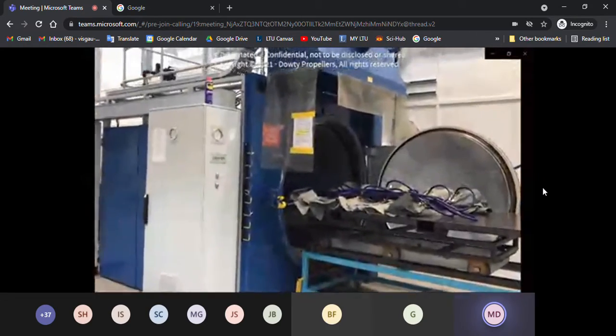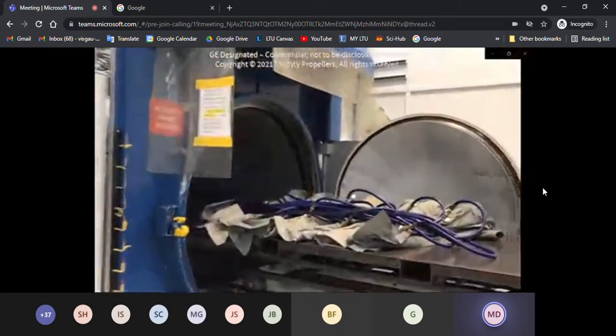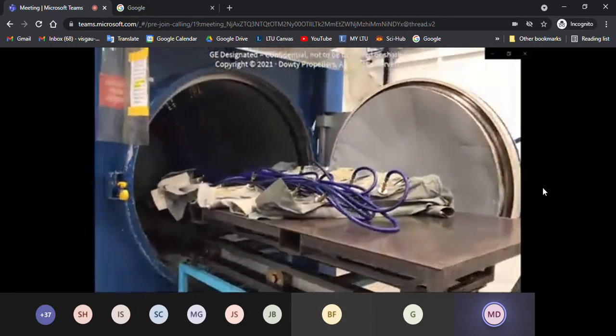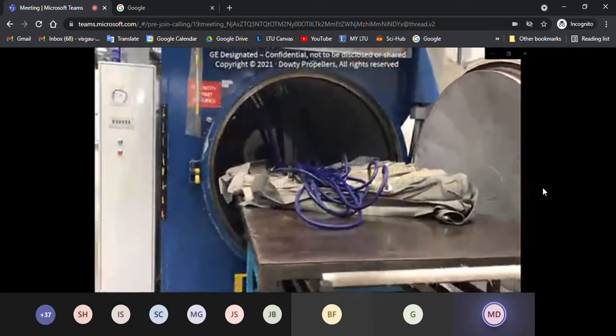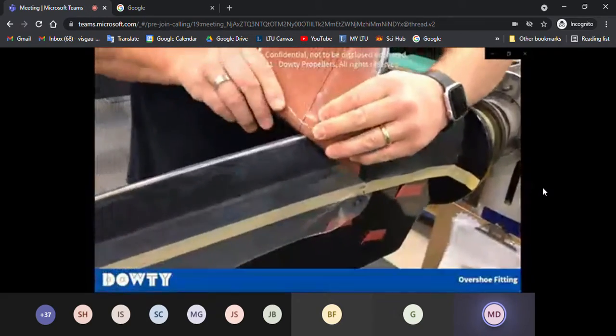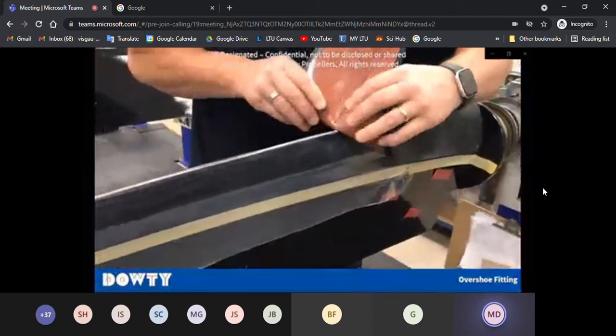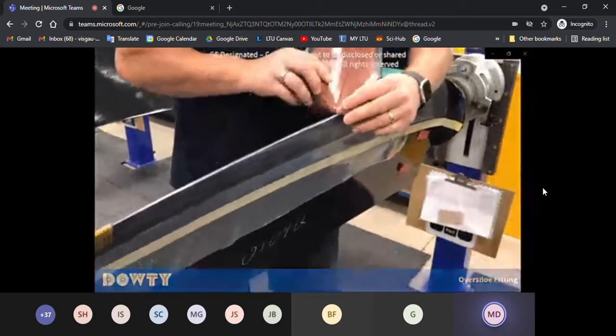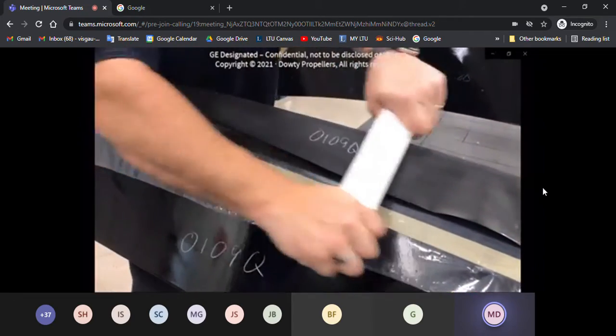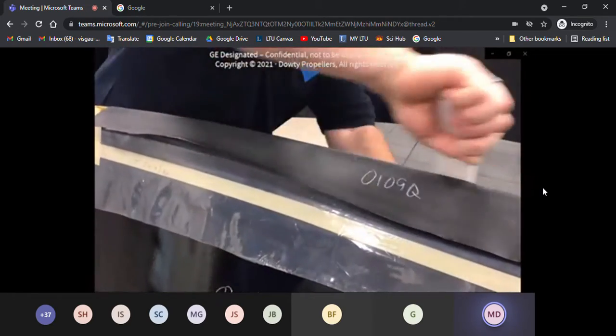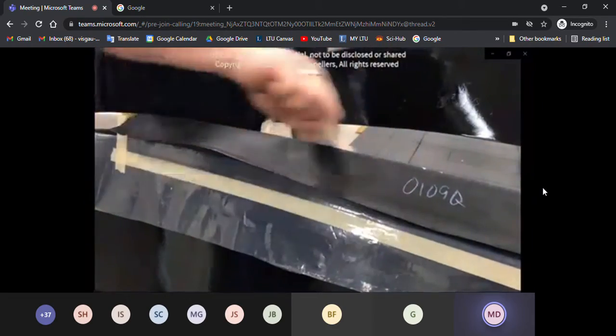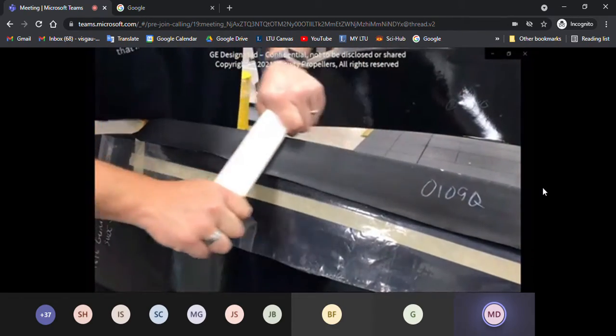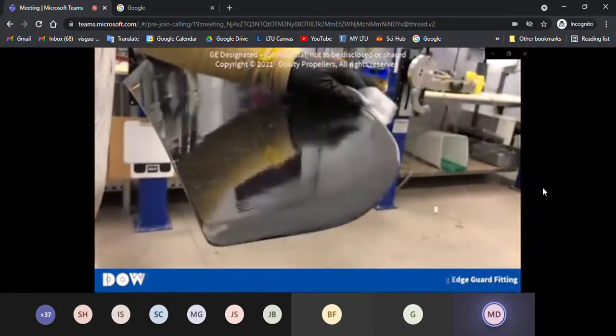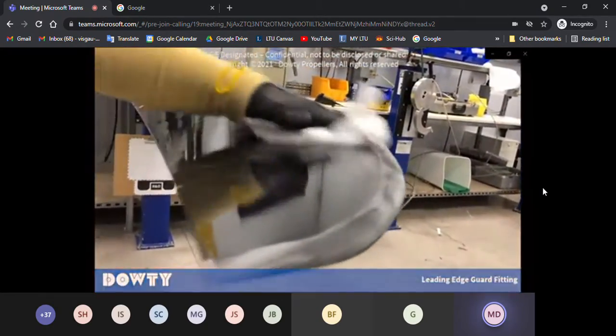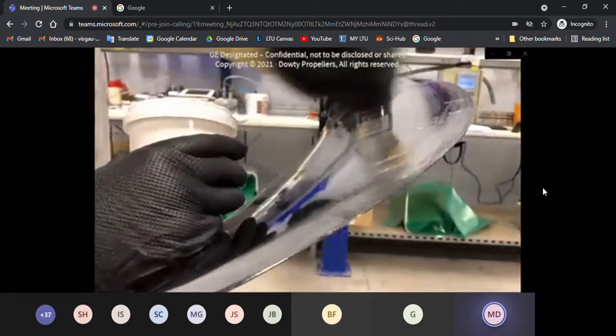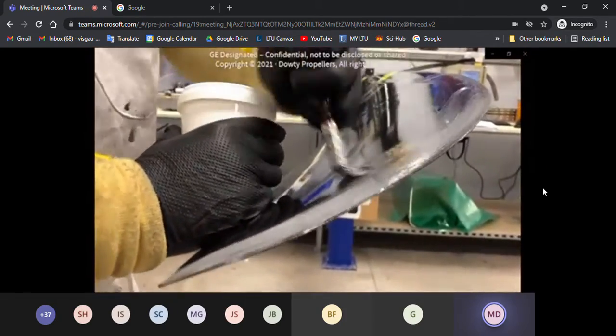The overshoes are vacuum bagged and cured in an autoclave, and you can see here a series of vacuum bags ready to go in the autoclave for cure. These are then laid up onto the blade by hand and bonded down with a special process that we use to attach them so that they perform their function during the service life of the blade, but can be easily removed at repair. You can see here a blade leading edge being prepared for bonding of the leading edge guard, which is attached. These are all still manual processes.